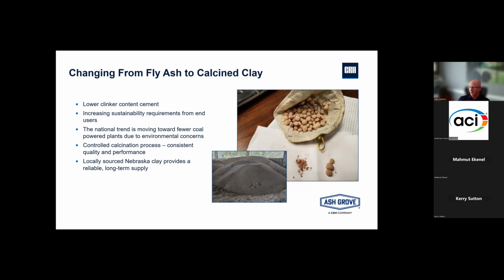And why do I say up until today? Well, there's nothing wrong with Duracem F, it continues to be used successfully, but being innovators here at Ash Grove, we're always looking for what's the next thing, right? We identified many years ago calcined clay as an opportunity not only to tackle the ASR issues successfully in that region, but also from a sustainability standpoint. We were starting to see increasing demands from the market in the latter part of the 2000s into the 2010s, and there were opportunities to leverage a calcined clay blended product at our Louisville plant. Not only does it mitigate ASR, it lowers the clinker content of the cement. We saw an opportunity there.